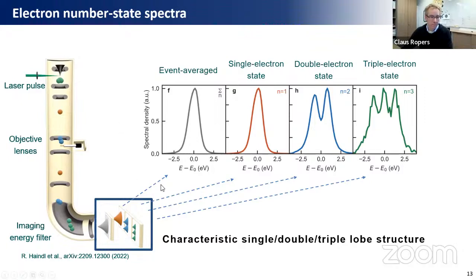Yeah. So now, as I said, we're in a condition where the average electron production rate for these conditions is a little bit less than 1. So the event average spectrum more or less looks like this. This is the energy distribution of the electrons, and we subtract the acceleration voltage of 200 kilo electron volts in this case. Okay, now if we only look at the events which contain 1 electron, this is a single lobed, slightly asymmetric spectrum, not so interesting, basically, as expected.